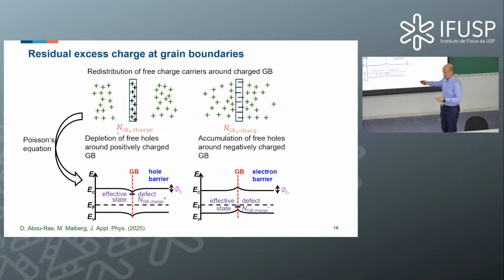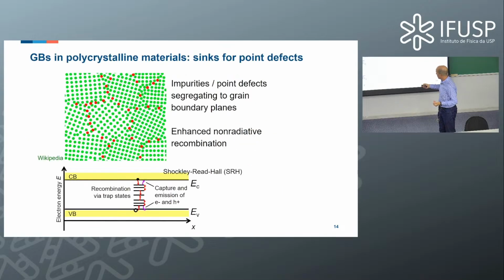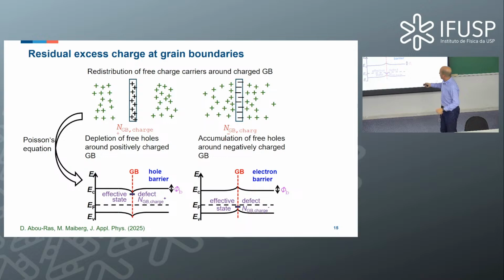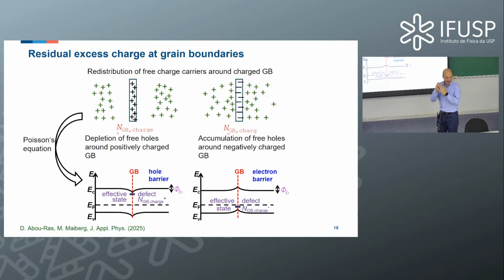So now you understand we have two details that contribute to the recombination, right? One is the Shockley-Read recombination, which is enhanced at the grain boundary, and one is the barrier at the grain boundary, because what does the barrier do? The barrier would either repel charge carriers, for holes here, or drive charge carriers towards the grain boundary. So it has a really strong effect on the recombination mechanism. Okay?